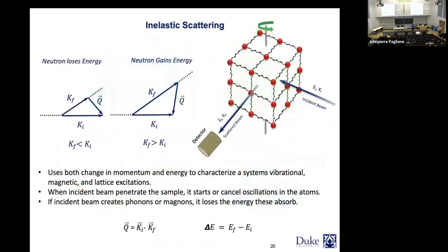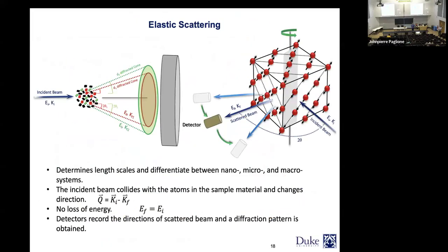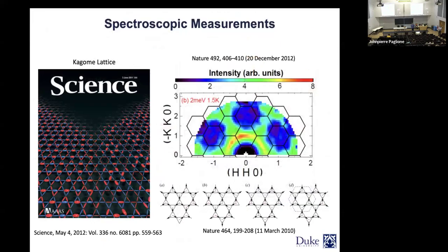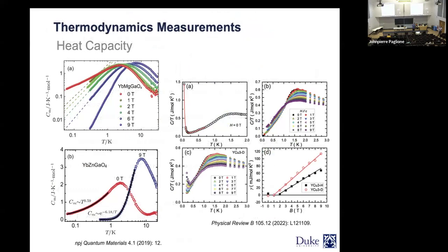How do you get that? As I mentioned, from the theory, your specific heat is going to have a power law associated with that. Depending on what component of the power law you get, first of all, it doesn't show any sharp feature or anything like that. The specific heat also tries to go to 0 at 0 field. And then it will have the power law relationship, either linear for a spinon Fermi surface, or quadratic for a Dirac.